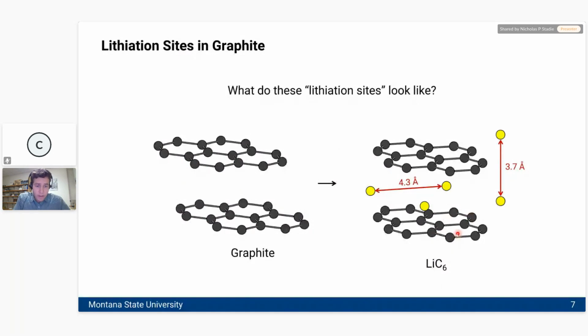Carbon itself is very lightweight and highly abundant. So this material represents a pretty effective solution for storing lithium. It's light, it's dense, and its electrochemical potential is extremely low. In fact, only a tenth of a volt higher than lithium metal. And you can't go lower than lithium metal, because if you do, you'll just plate lithium metal onto whatever your electrode is made out of.